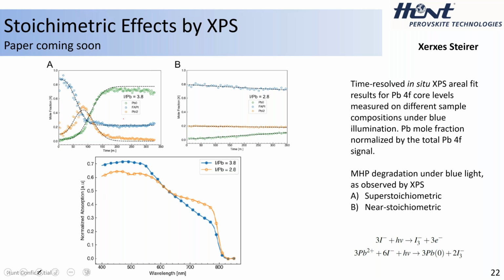How do these stoichiometric effects really register on the surface? To see exactly what they're doing on the surface, not more collectively, grossly in the bulk perspective like you see with XRD, we utilize XPS, X-ray photoelectron spectroscopy. And what we're doing here is we are taking two different stoichiometries of perovskite. So a iodide to lead ratio of 3.8 versus a iodide to lead ratio of 2.8. So 3.8 being super stoichiometric and 2.8 being what we call near stoichiometric. It's within the error of the fitting of the XPS system. So 2.8 plus or minus, 3.8 plus or minus. And then we bombard these samples under constant XPS measurement with blue light and see how the samples change.